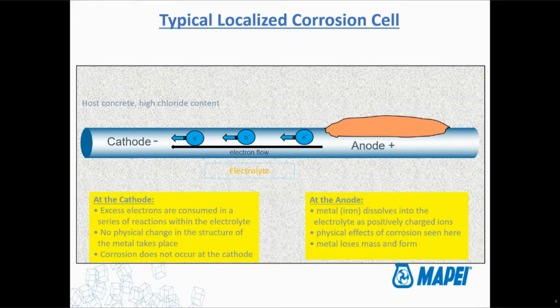So basically what happened is you have this existing bridge deck and it's been sitting there for 30, 40 years. It's been absorbing chlorides for all that time. So the whole bridge deck is very high in chloride, just from being in use over the years. But now you've replaced this really small patch area. And so that really small patch area is very, very low in chloride content.